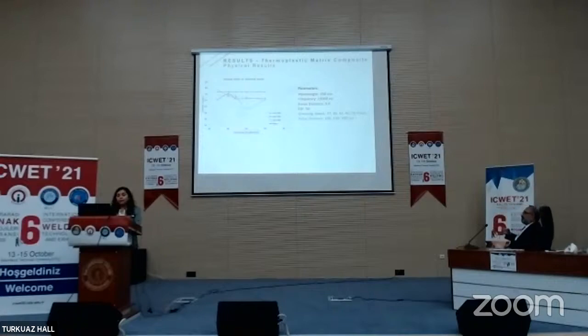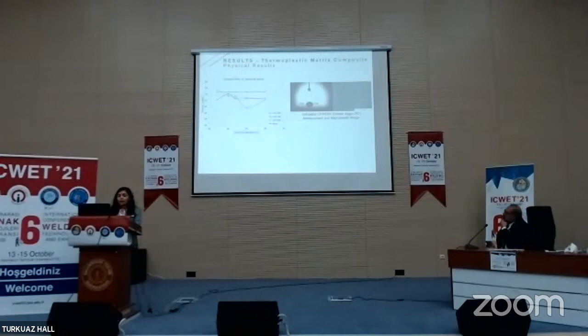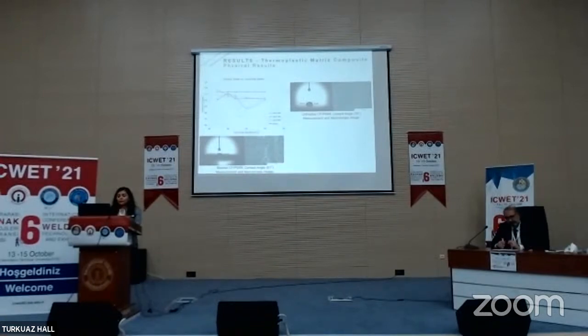We understand that low scanning speed does not provide a hydrophilic surface at each pulse distance. Some parameters may even impair the wettability of the bare surface. I would like to show three water contact angle measurements and their macroscopic analysis. The first one is the untreated surface, and it has a 76 degree contact angle. The second one is blasted by glass bead particles, with nearly 61-degree contact angle gained by this surface treatment.